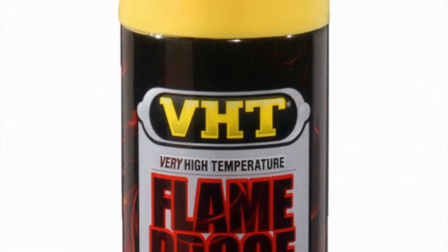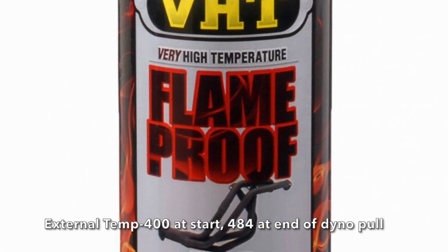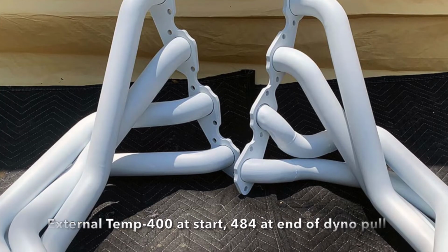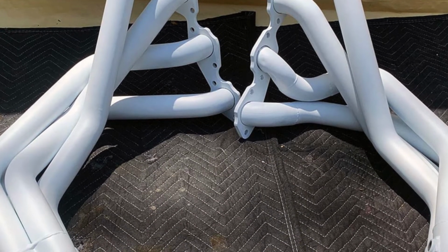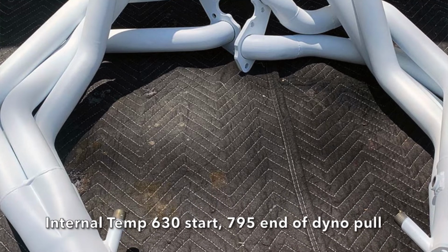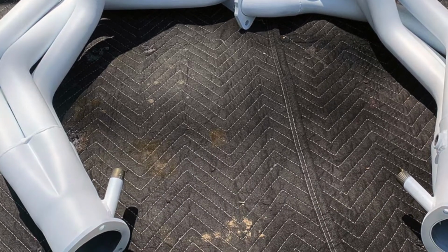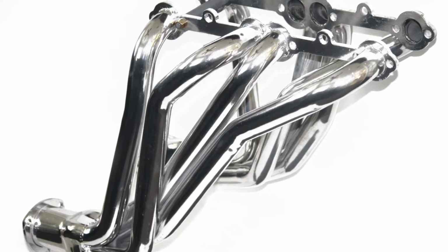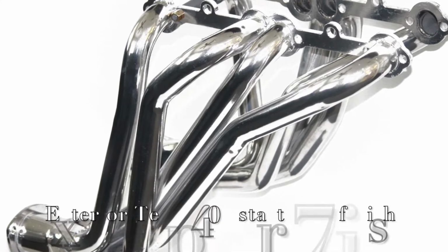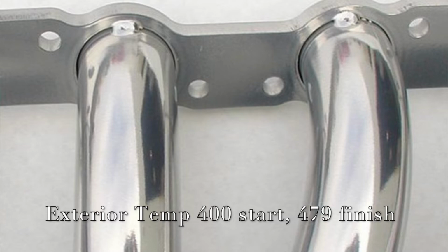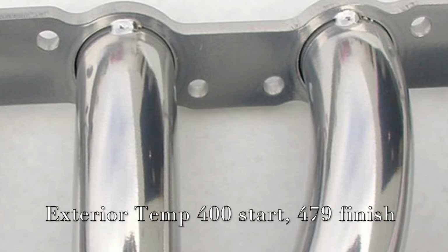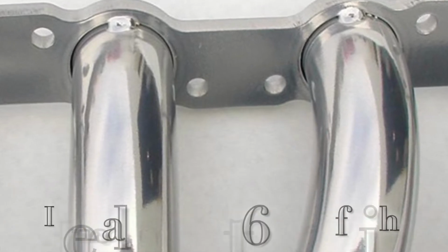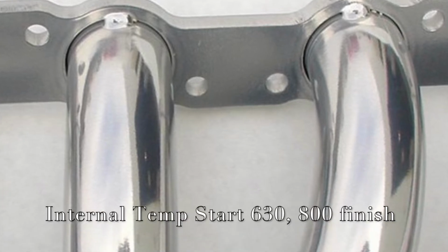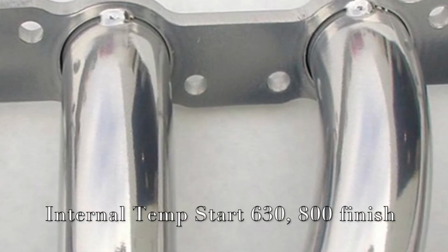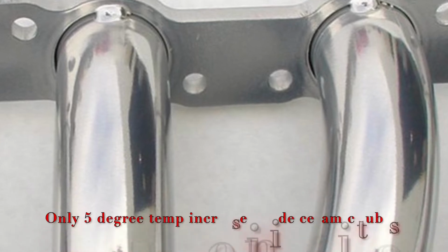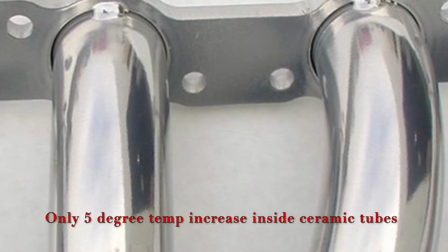Painted headers on a dyno cell, the exterior temperature ranged from 400 at the beginning of the pull to 484. The internal or the EGT temperatures ran from 630 at the start of the pull to 795. Ceramic coated headers, the thermal barrier coating, at the beginning of the pull, the exterior temperature was again at 400 degrees and it went up to 479 by 6,800 RPMs. The internal temperature started at 630 degrees, same as the plain painted header, and went up to 800 degrees. So there was a 5-degree temperature difference inside the tube of the ceramic coated header.